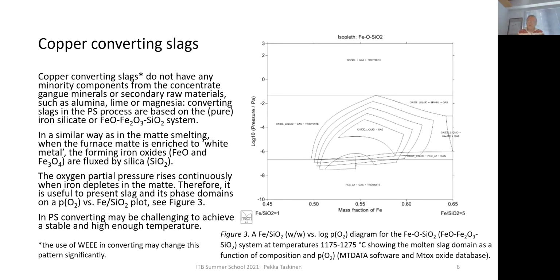So slag formation, how it is carried out, it's not thermodynamics, it's not actually of any other scientific issue. It is more or less practicality, how the operation is carried out at the smelter, how the stable temperature is achieved as early as possible, and how it is maintained so that the charge does not overheat, how cold coolants are added, and in which way silica sand is added into converting when the converting is going on, when more and more iron is transferred from matte to the slag as oxide.